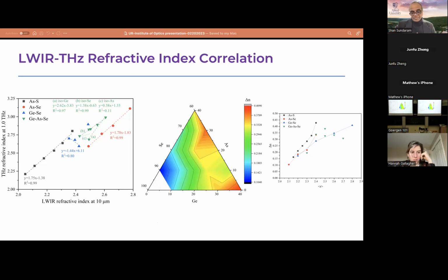So this is one example. We did a lot of this correlation in borosilicate glasses, correlating visible refractive index and absorption coefficients to terahertz refractive index and absorption coefficient too. We found a lot of good correlations there. But for the chalcogenides, because they have high transmittance values, they're highly transparent in long wave IR, we picked up the long wave IR refractive index values and correlated them to terahertz values. So you see for certain families like arsenic sulfide, arsenic selenide, they have a pretty good linear trend happening. That means we can correlate one property in one frequency range to the corresponding property in another frequency spectrum in the same family of material. So this will also make a material multifunctional.